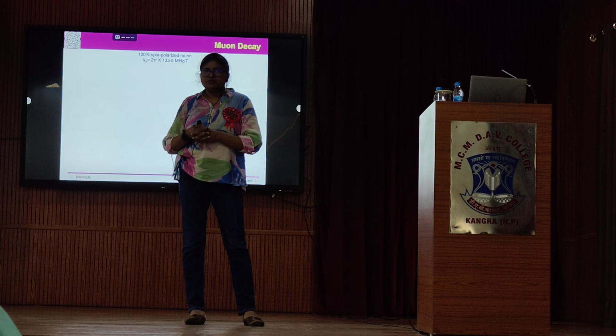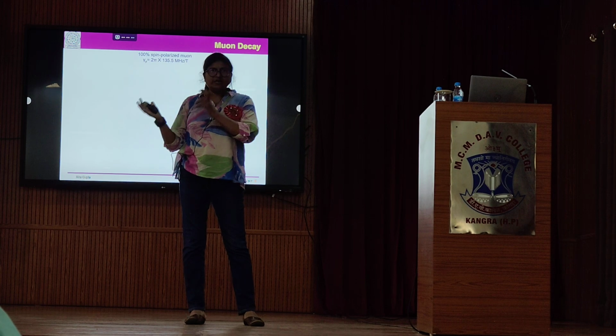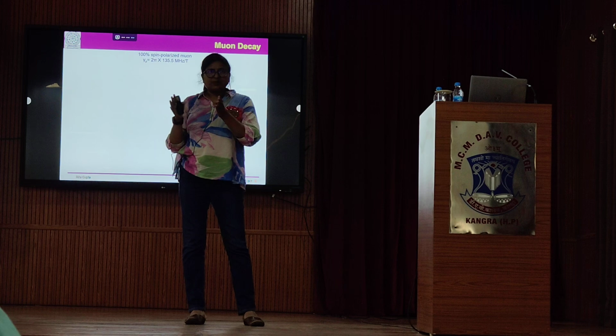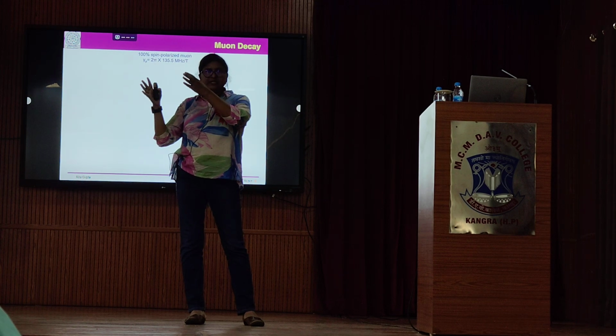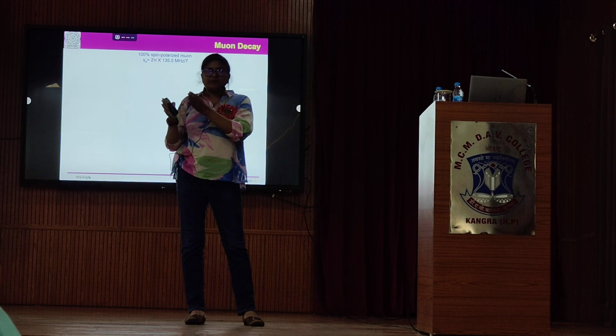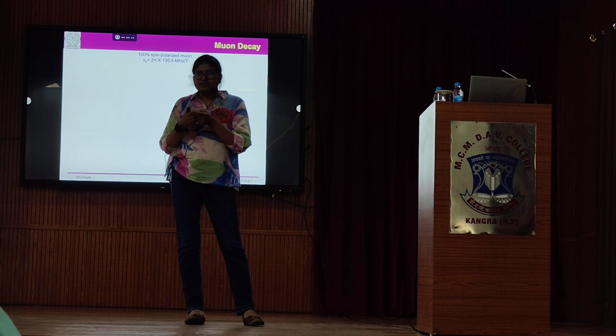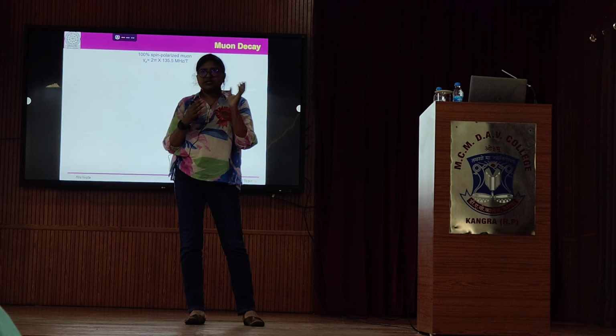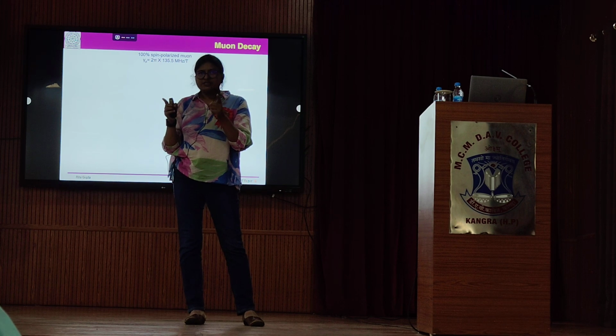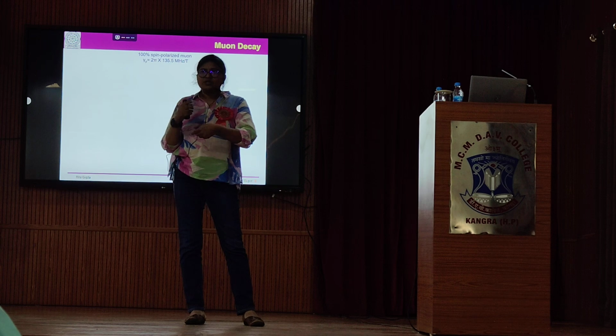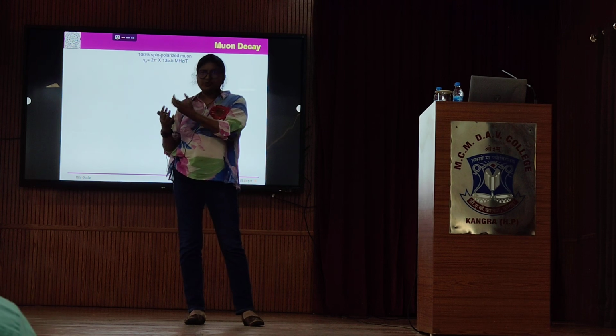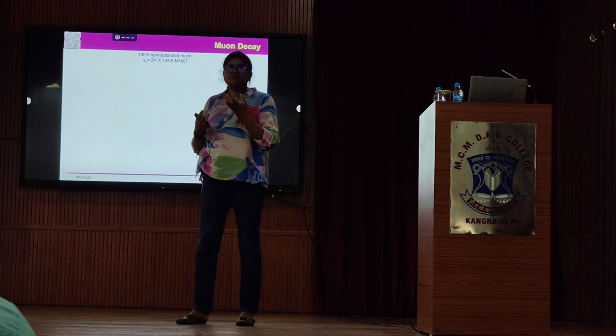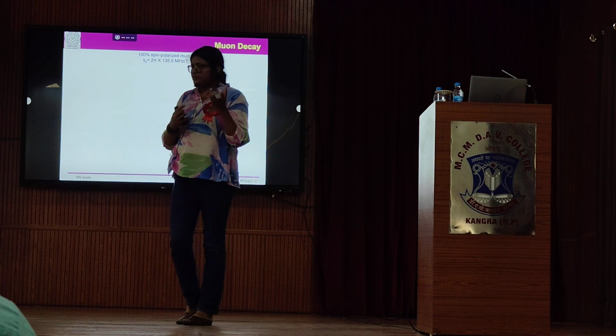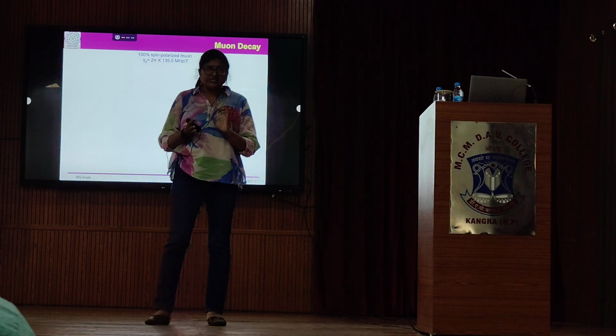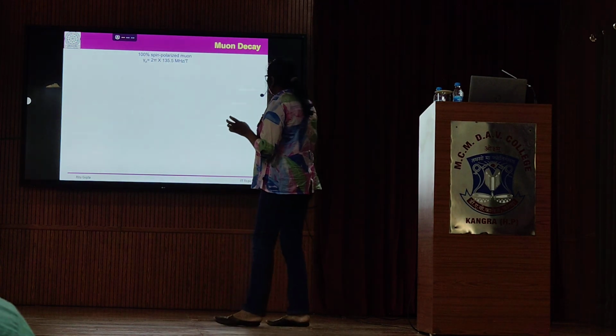What happens, so you have two types of superconductor, type 1 and type 2. So in type 1, there is an upper critical field above which the material becomes completely normal. But in type 2 superconductor, what happens? There are two critical fields. Below the lower critical field, the material is completely in the Meissner state, and between the two critical fields, there is a vortex state. So the vortex state is kind of, there are some regions where you have magnetic field, there are some regions where you have normal state. So it's kind of a mixed state. Okay. So you want to probe that mixed state, and what we did, we used muons.